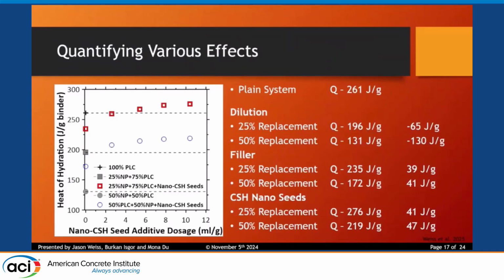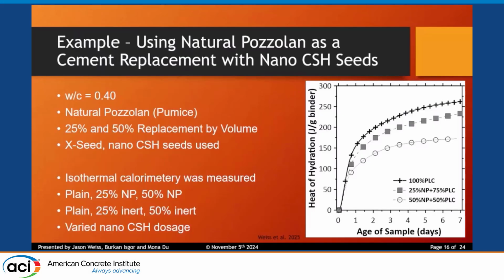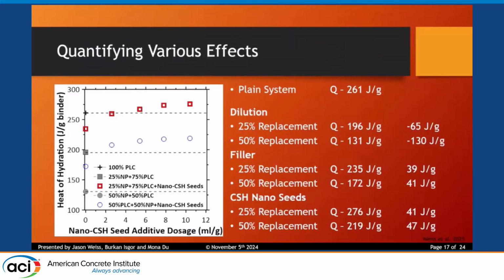Now, if we start looking at these longer term values, we'll go out to 7 days, for example, although we could take this out longer, we could actually look at the heat of hydration in the system. For our plain system, we might be up here around 260 joules per gram of cement. If I replace 25% of it, I drop down to this value right here, which is about 196, and if I replace 50% of it, it's 130. So this is the heat that I need to make up to get back to this value here. How am I going to make that heat up?